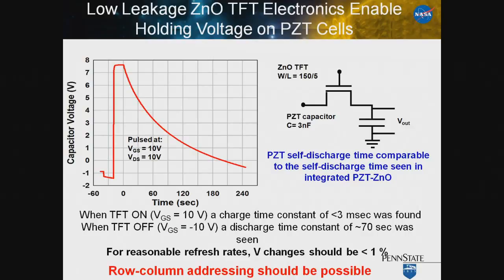The next set of experiments that we did was to try and demonstrate whether we could actually use these thin film transistors for a row column address. And so I show here data for a zinc oxide thin film transistor prepared on a PZT actuated glass optic. And what we've done is to basically modulate the voltage coming in to the thin film transistor. So at this point, we turn the transistor on, and we hold the voltage then for some time. What you're measuring here is the voltage across the PZT capacitor. We were able to turn individual cells on in the order of 3 milliseconds.